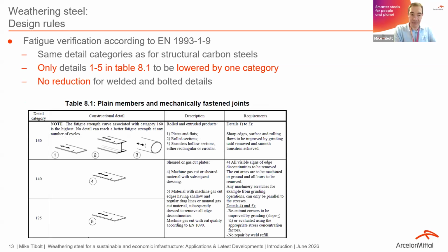For welded and bolted details, because here the presence of the geometrical notch of the bolt, of the hole, and of the weld seam is higher than from the roughness of the surface, we do not need to apply any reduction. So we take the detail category as for non-weathering structural steel, as for non-weathering structural steel.